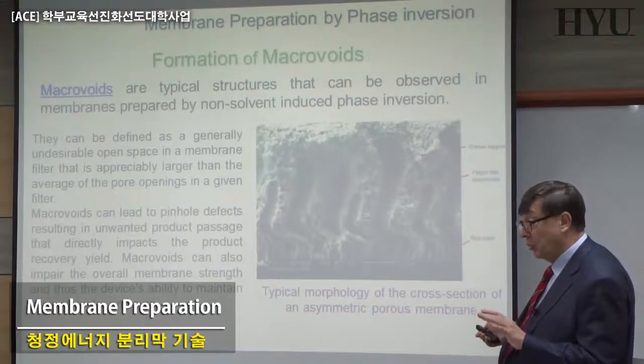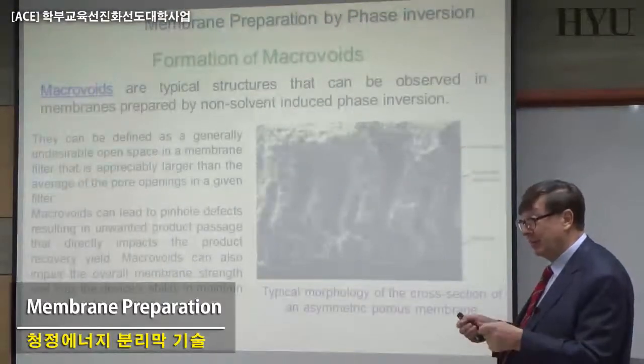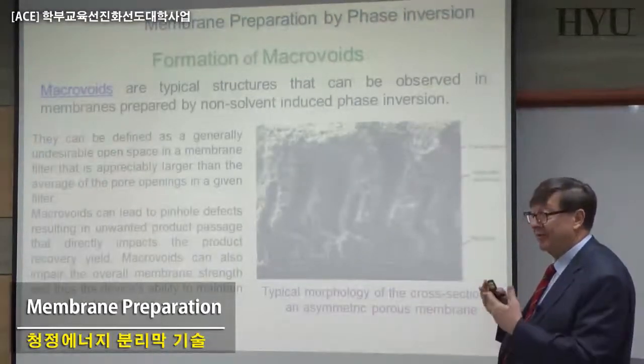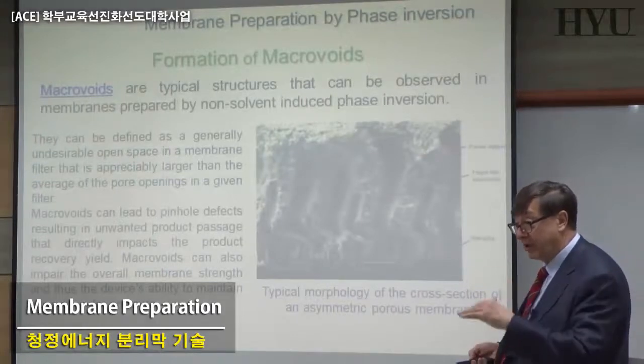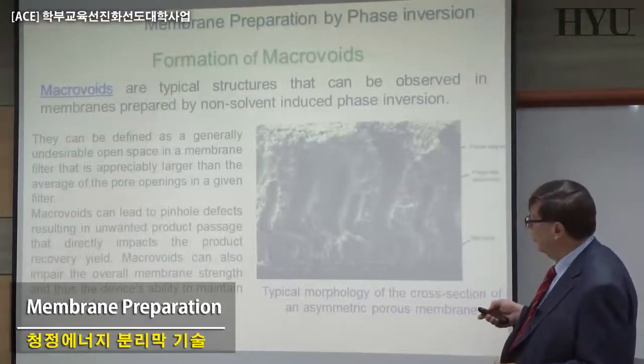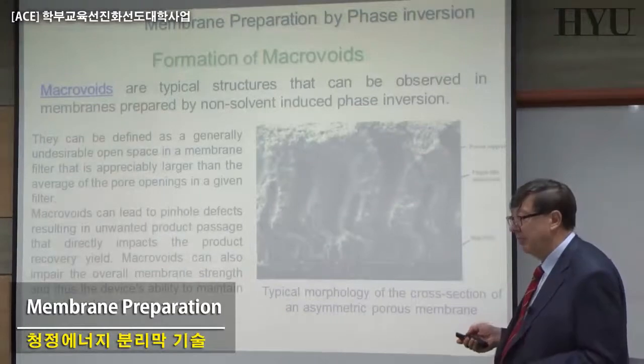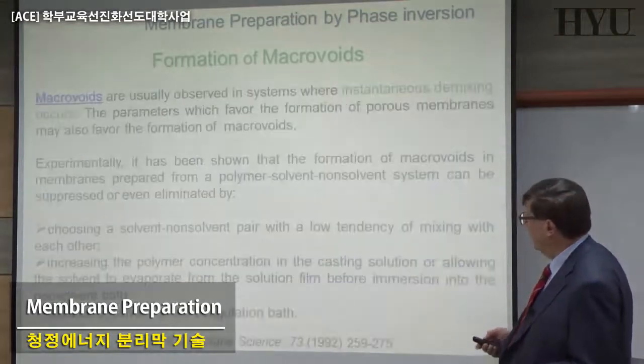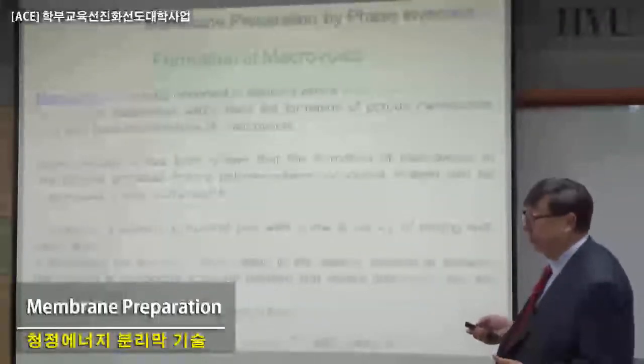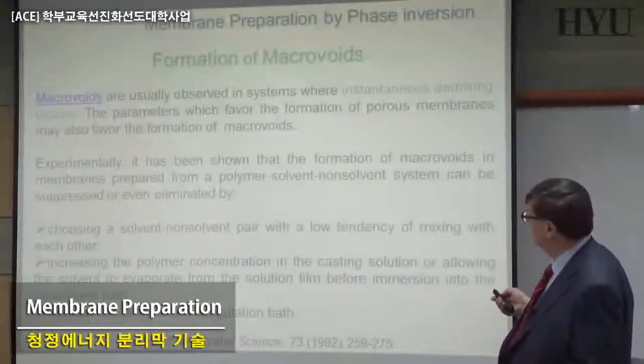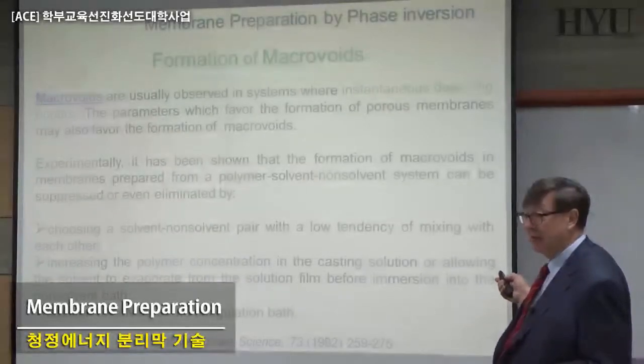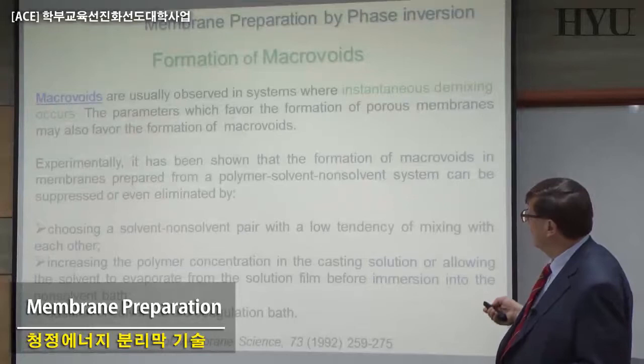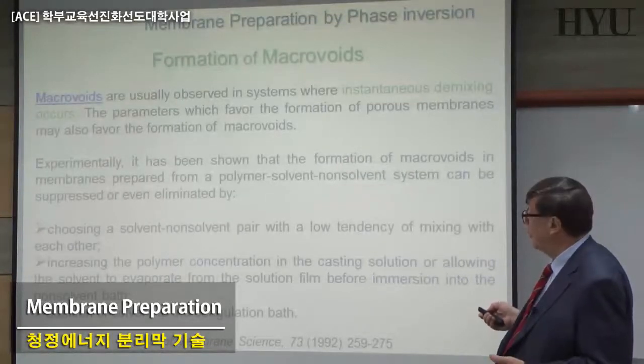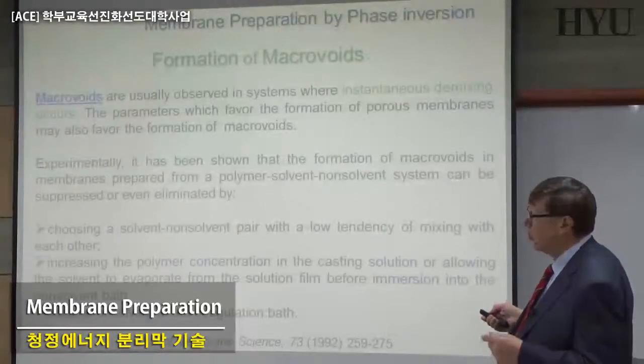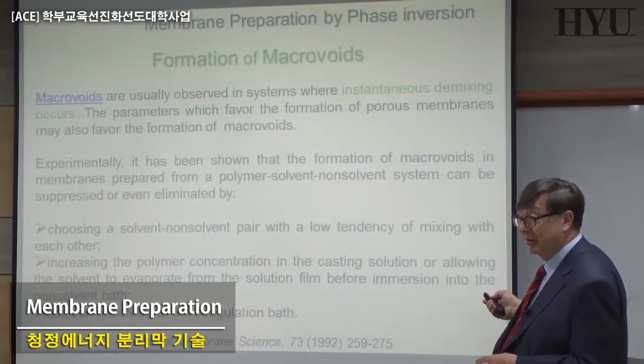Macrovoids, in general, we don't want to have, because mechanical properties are changing, and the lifetime of your membrane, stability, compaction, etc., are problems. So this is one of the things, how to avoid the macrovoid formation, and there are different ways of doing this. Macrovoids normally are observed in systems where instantaneous demixing is taking place. And that means you can find a way to try to change what is inducing this instantaneous demixing, as we saw before.